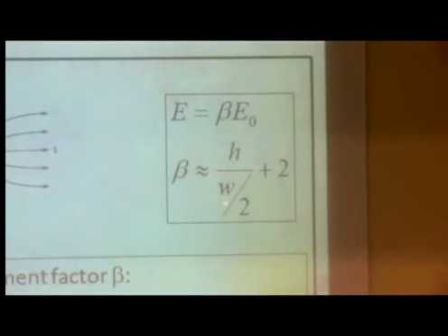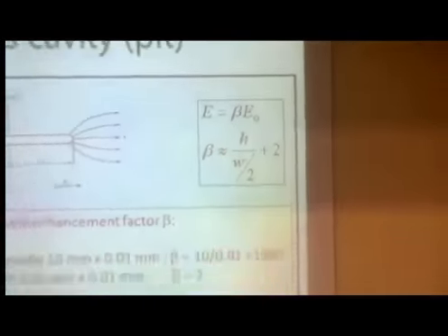But let's make a very simple calculation again. I like simple things, as you know now. This is textbook stuff. If we have a protrusion here, the amount of field enhancement depends on the aspect ratio. The larger the aspect ratio, the larger the field. And roughly, this is the amount of field enhancement we have. The length of the protrusion, and this is the radius. Let us assume a needle with a length of 10 millimeter, 10 micron radius. We get 1,000 times field enhancement at the tip. So, easy enough. Now we take this starting cavity, which only has a radius of 10 micron, and we get field enhancement of 3, maybe 10. So normally we would be far away from the conditions we would have at the needle.